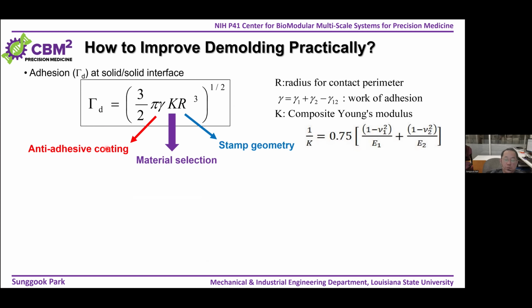Okay, so what can we do? We can do several things. In order to reduce this work of adhesion or surface energy, we can apply an anti-adhesive coating layer. Okay, and normally R is the contact area, which is determined by the stamp geometry. So there is not a lot we can do here, but we can also control K, which is the composite Young's modulus. Okay, basically we can reduce this composite Young's modulus by properly selecting the materials.